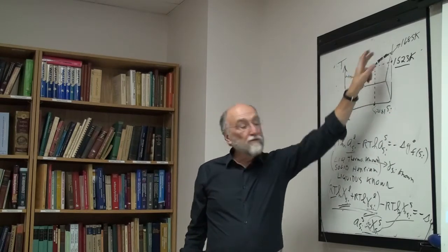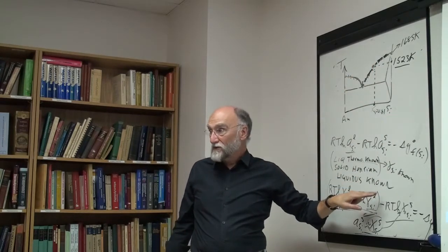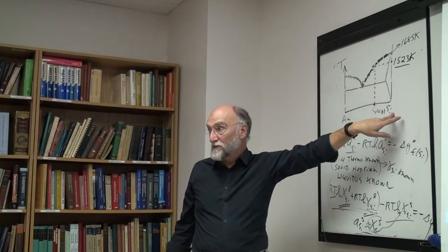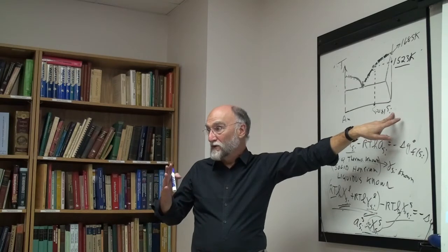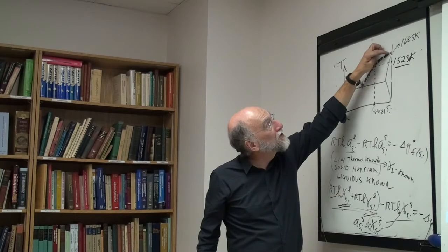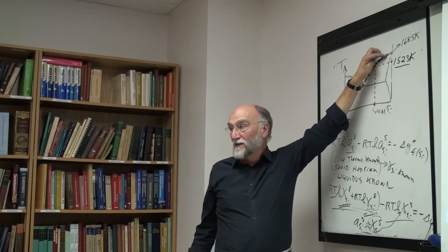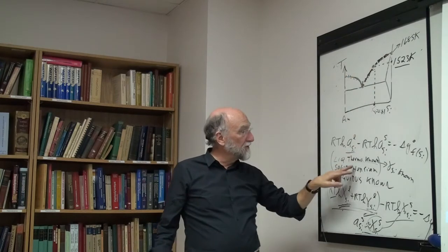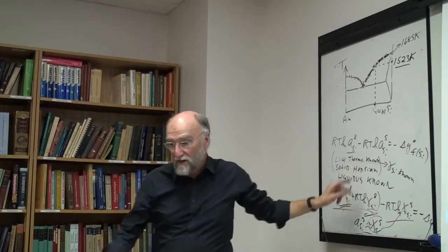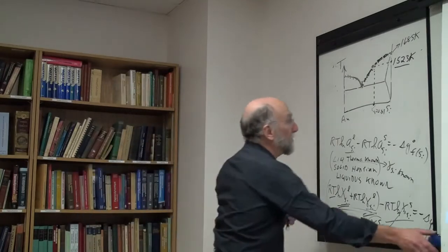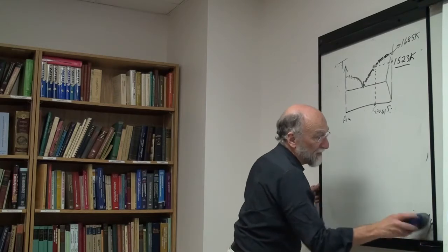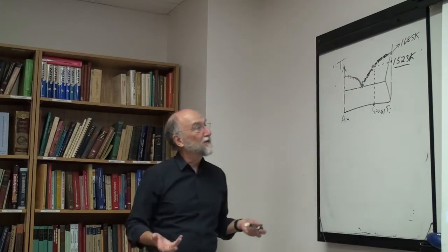In that case, the liquid phase is Raoultian, because you know Raoult's law: as any phase approaches the pure solvent, the activity approaches 1. So if I'm in the limiting region, in the first 2–3% on this liquidus line, I don't have to know the thermodynamic properties of the liquid, because I can assume that the liquid is ideal. In that case, I can assume both the solid and liquid are ideal.